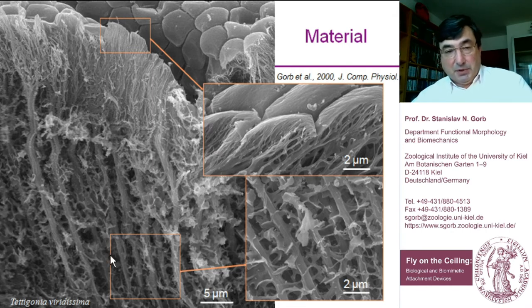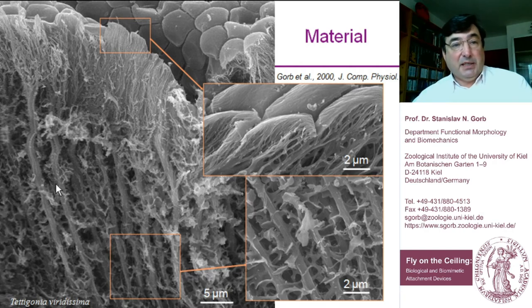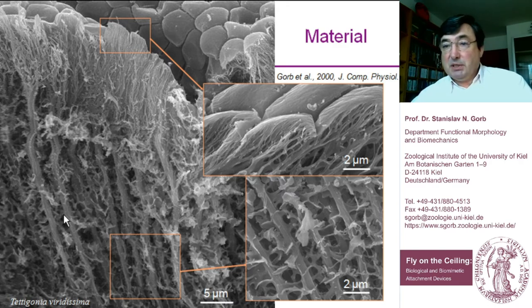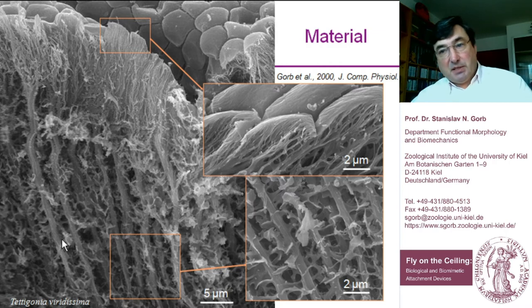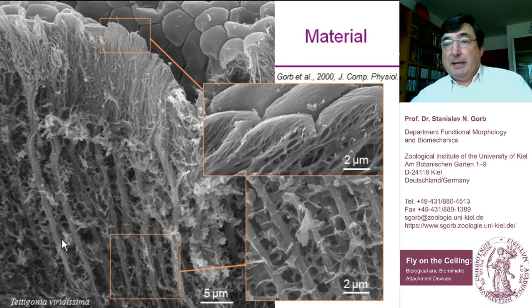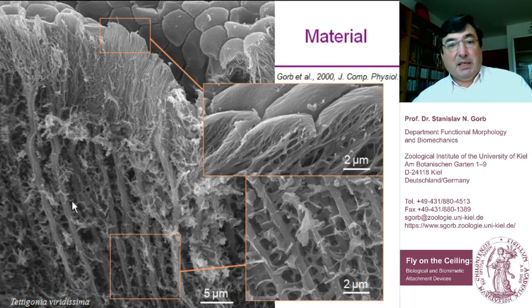This is the grasshopper with a smooth system — the arolium. In binocular microscopy these structures look quite smooth, but if you use cryo-SEM and freeze and break them, you see that the internal structure is like fibers branching many times near the surface — a hierarchical internal structure. The gaps between the fibers are filled with fluid, so you have a stiff chitin-based material with high aspect ratio that makes the whole system very floppy and adaptable, with viscoelastic properties. The material behaves like a pudding that adapts to different surface types and generates fluid in the contact area.